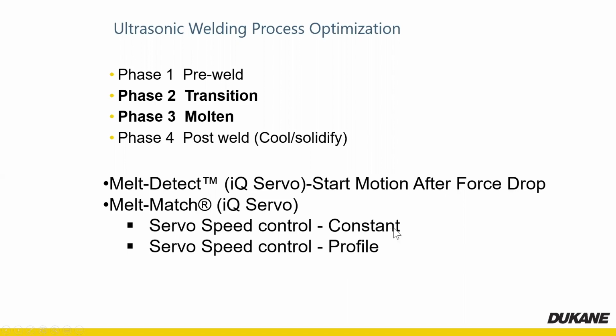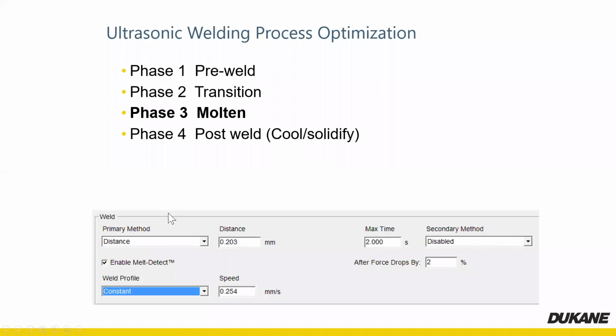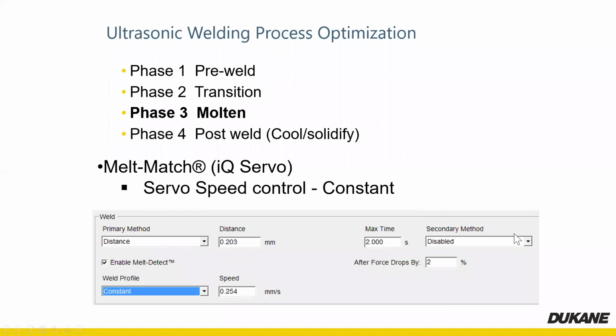For most applications, I actually set these up to use a constant speed. With a constant speed, you can usually get sufficient strength, well beyond what's needed for these applications, but every now and again there's an application where using a profiled velocity really has some benefits. So in this instance, we've got a constant velocity set of 0.254 millimeters per second, and that's perfectly acceptable, and in a lot of applications that's what we've got set.